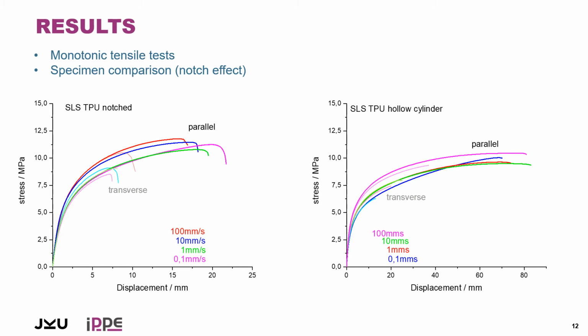Here you see the results of the monotonic tensile test and the comparison of the notched specimens with the hollow cylinder, does it mean the unnotched specimens, for both printing orientations. You see the difference, and if we compare stiffness at low strains, the strength, the maximum load, or the fracture strain, then we see that the highest difference between parallel and transverse we can recognize in the fracture strain. Does it mean the specimens where the printing orientation was in the loading direction revealed significantly higher fracture strain values for both materials.